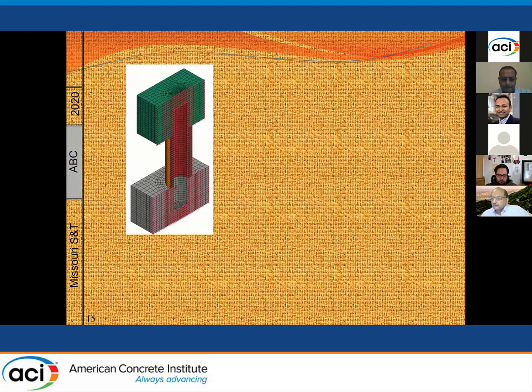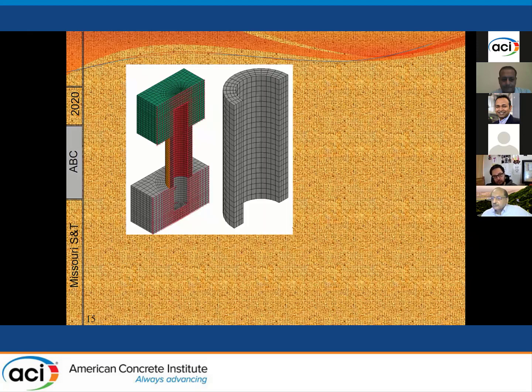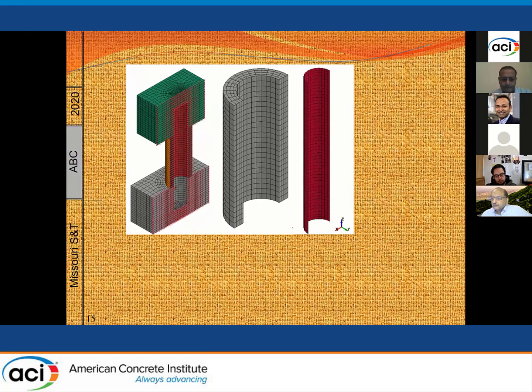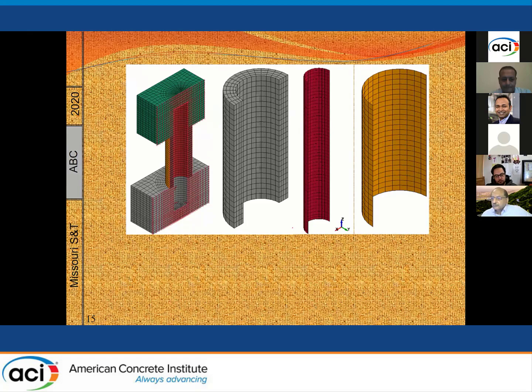And then we developed the finite element models. We use the finite element models for different things, but one of them is to investigate the shear capacity of the columns. Here the column is symmetric, so we only modeled half of the column. So we have a vertical plane of symmetry. And for concrete, this is concrete that's sandwiched between the different pipes. So for the concrete, we used solid elements. And then for the inner steel, it's a shell element. And then the FRP is also another shell element.